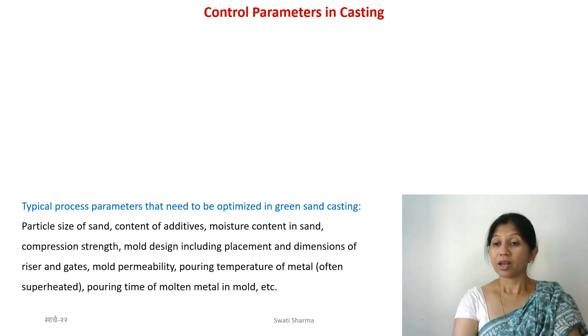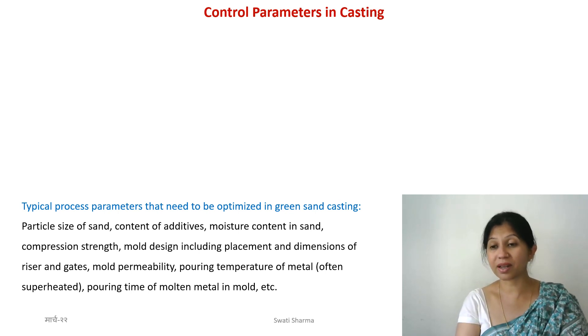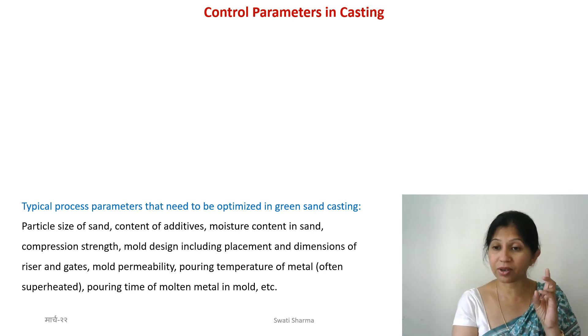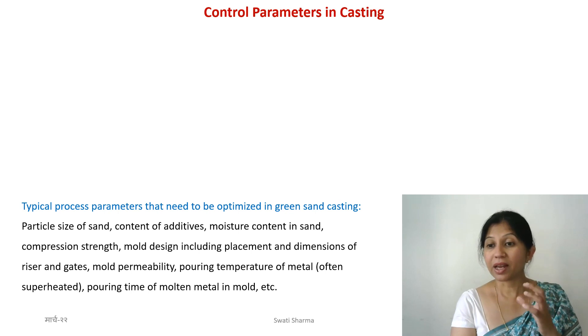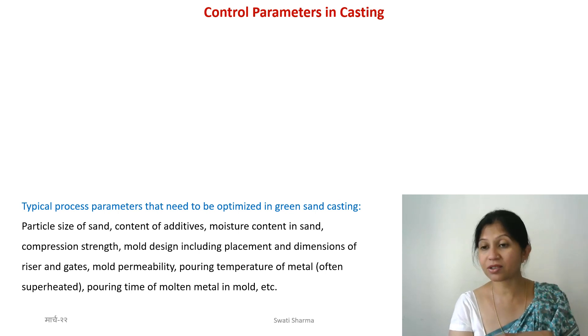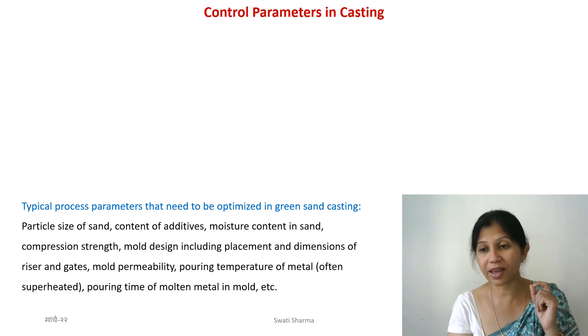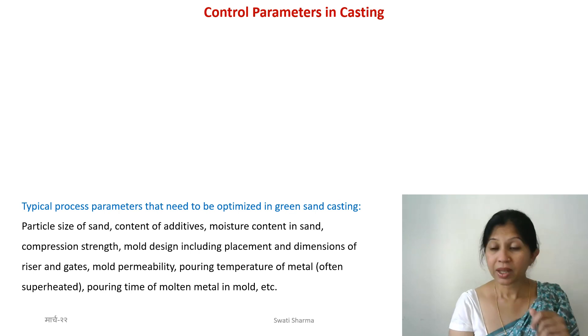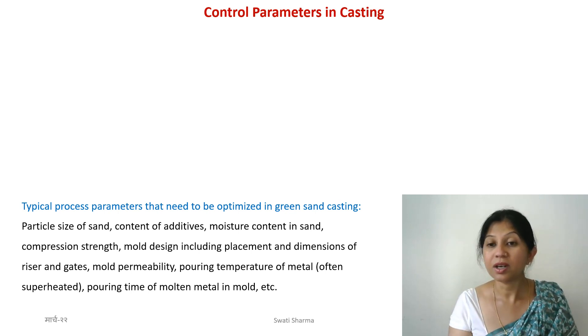Moisture content is another very important parameter. You might think moisture won't make much difference because of organic binders, but a lot of defects occur if there is moisture in the sand. Remember, we are working at very high temperatures — water will evaporate, and any gases present in the system (even from organic impurities in the metal) can cause bubbles and defects. However, the sand should not be completely dry either, as it will not bind properly.